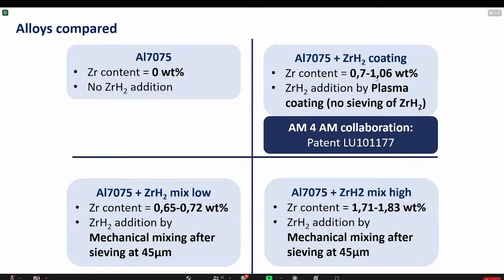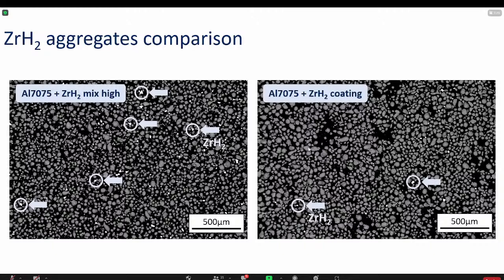Finally, I will also compare the first 3 powders with a coated powder, in which the zirconium hydride is added thanks to a plasma process patented by AM4AM, a startup in Luxembourg. It uses a plasma process to graft ceramic powder on the surface of the aluminum 7075 powder. Concerning the powder, I have compared the plasma coated powder with the mechanically mixed powder, and I have shown that there are far fewer big zirconium hydride aggregates, which are detrimental for the mechanical properties, in the coated powder.